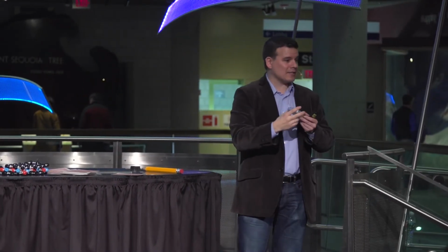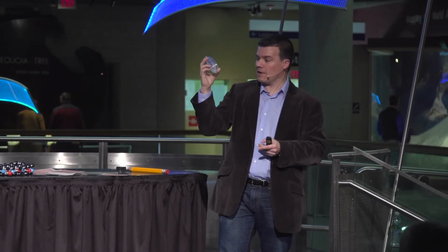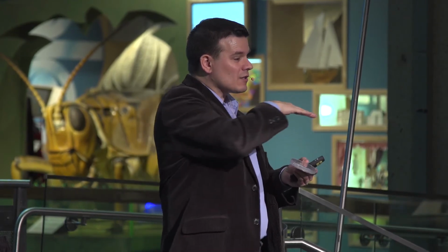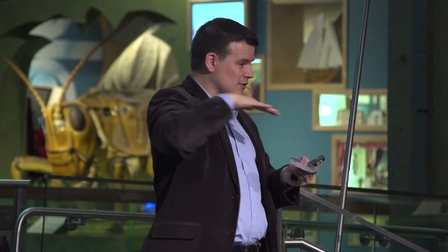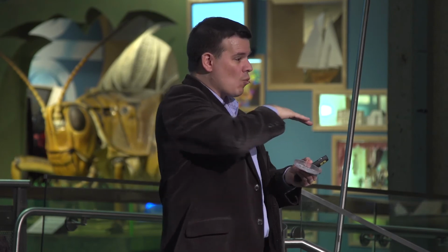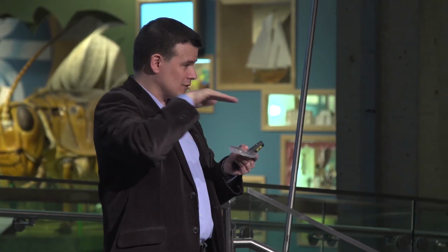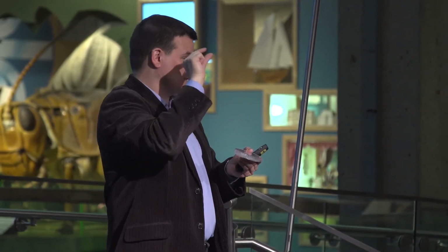I have here a very similar material, molybdenum disulfide. I'm going to pass it around so that you can see it. What you will see here in this box is some yellowish thin layer and another yellowish thin layer across. You're seeing 1 monolayer of molybdenum disulfide, a semiconductor very similar to this one, and another one across. In the area where they overlap, it's 2 layers, and it's thicker, and there is a bit more contrast.